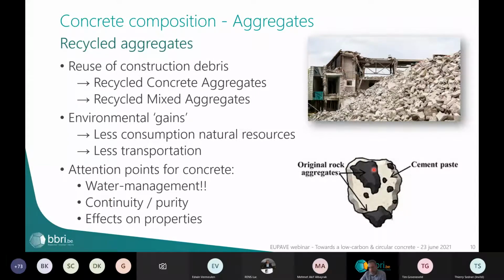When we look at recycled concrete aggregates, schematically here on the right, you can see one of those aggregates. In fact, it is composed of the original rock aggregates in the primary concrete, surrounded by cement paste. So instead of the original rock aggregate, you get a material that is composed of the original rock aggregates and a mortar. So of course, this recycled concrete aggregate is going to absorb more water. The cement paste is more porous than the original rock aggregate, so it is going to absorb a lot of water. So in the concrete mix, you have to take into account the high water absorption of these aggregates.